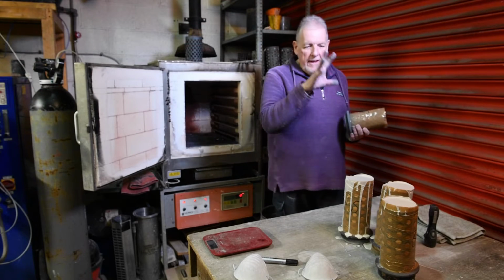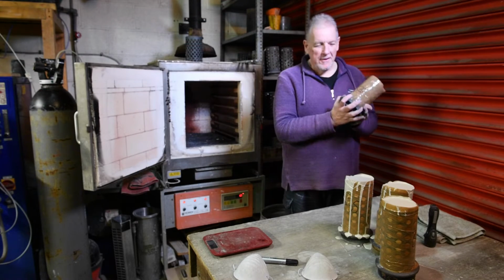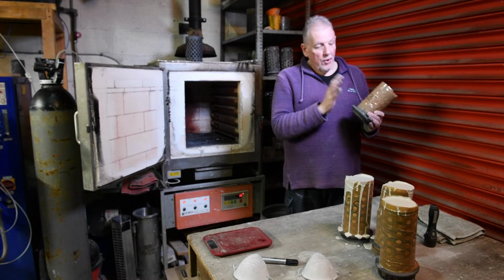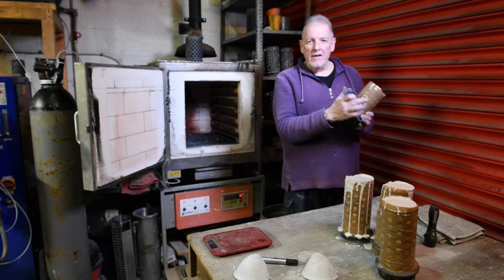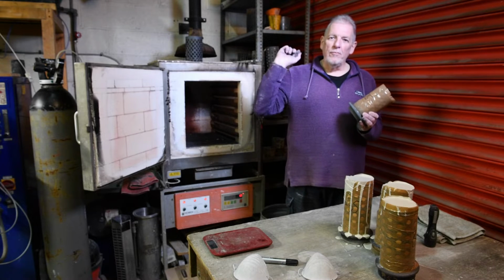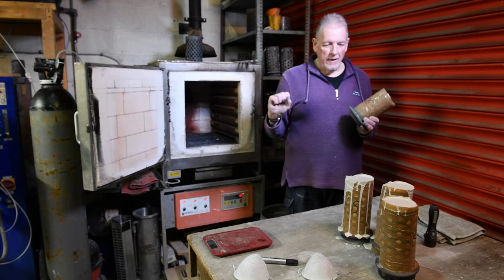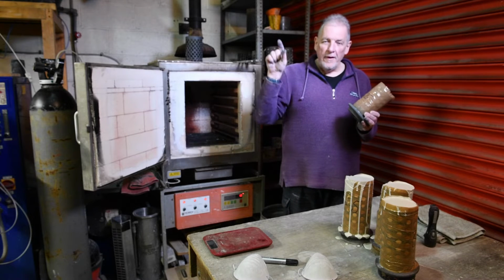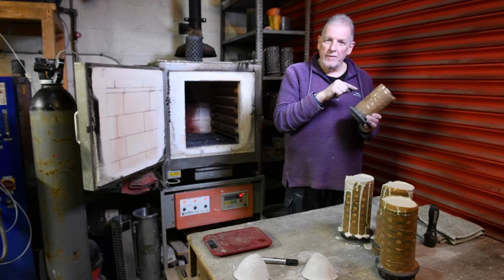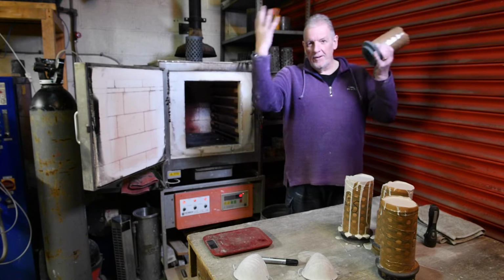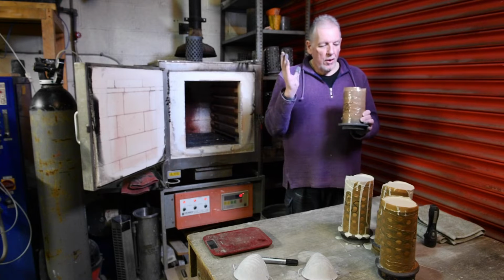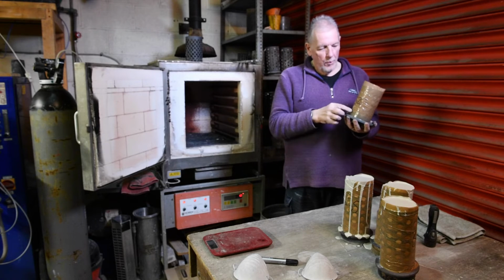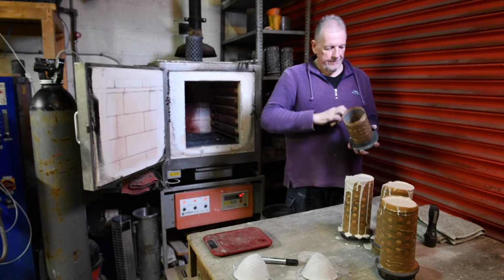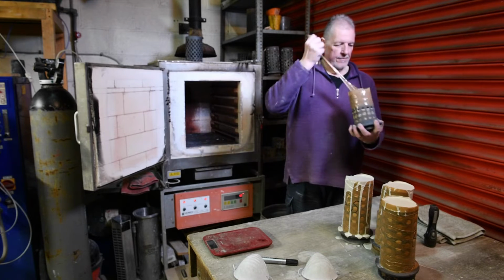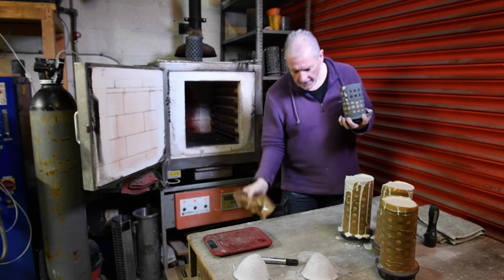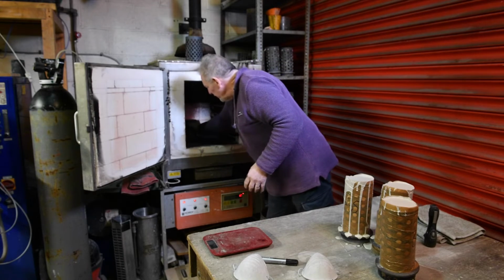As these have to wait for an hour and a half to set, again in Blue Peter fashion, I prepared one earlier to show you exactly how it's done. Now the weight that is written on here will be written on a whiteboard. We'll show a picture of it in a little while, so that we know which flask has to have how much metal. Otherwise you could have too much metal or too little metal to fill the cavities. Once they're set and we've written the weights onto the board, we can remove the tape and then the flask goes into the kiln.